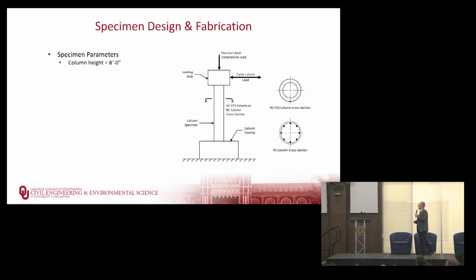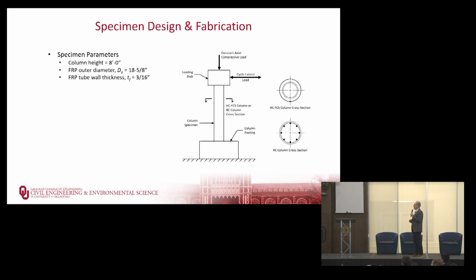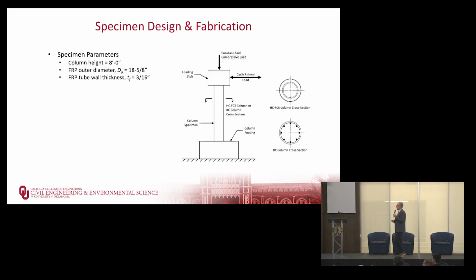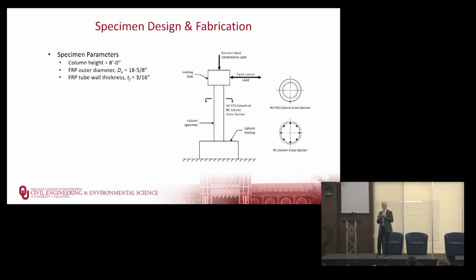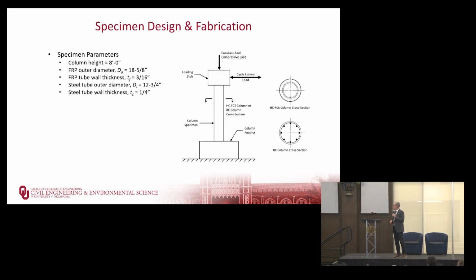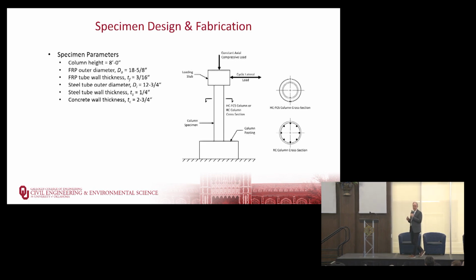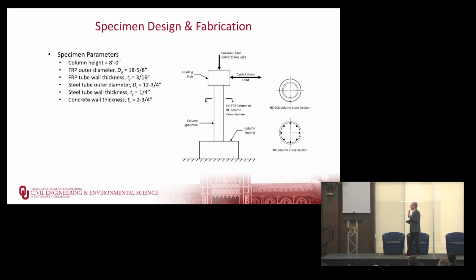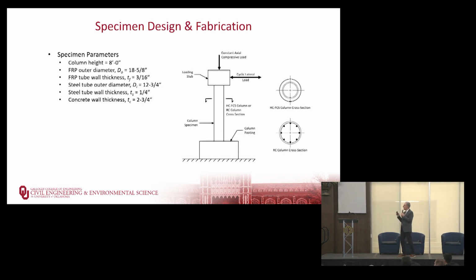So our column was 8 foot tall. The FRP diameter was, because of standard sizes, we want an 18-inch diameter column, it's about 18 5/8 of an inch. The tube thickness of 3/16, we went with the thinner value. The steel tube was 12 3/4 of an inch diameter, again standard sizes, 1/4 inch thick. Again, we went with the thinner ones for these first set of specimens. And that gave us a concrete wall thickness of 2 3/4 of an inch, which is not a lot, but we'll talk about that in a minute.